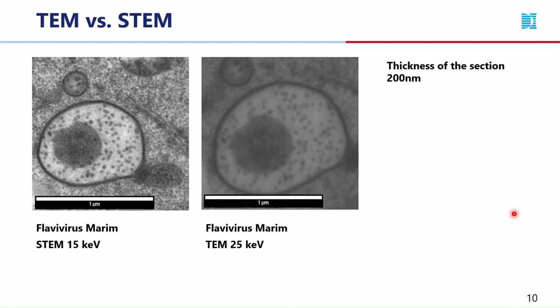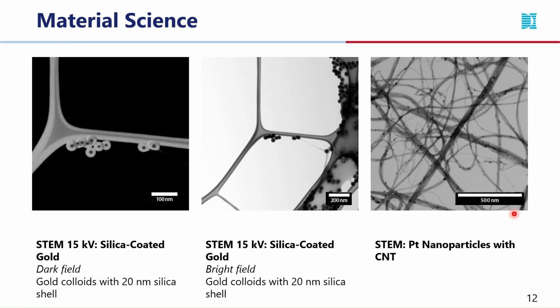Here is an example of very thick sections of about 200 nanometers, which can serve as a proof of STEM capability to handle blurred TEM images caused by the interaction of the electron beam with the sample. But STEM provides very nice images also for material science, especially in the case of light elements, and you can also use both imaging modes, dark field and bright field.